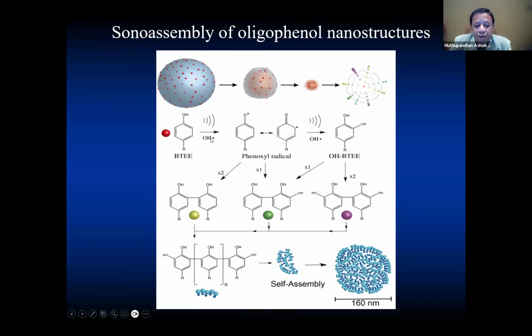It involves the hydroxyl radicals that we generate, but also the heat that we generate when the bubbles are collapsing. So a combination of heat at the interface of the bubble and the radicals that we generate leads to the formation of dimers, trimers, and oligomers, which self-assemble to form these nanoparticles.